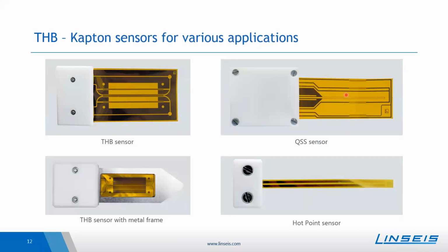We have a lot of different sensors available for the THB. These can be classified into two groups. So we have Kapton foil sensors, which are shown here, and we have sensors based on a ceramic substrate. These are for the high temperature applications. The Kapton foil sensors can measure maximum up to 200 degrees Celsius under air, and this range can be extended with an inert gas atmosphere up to 300.